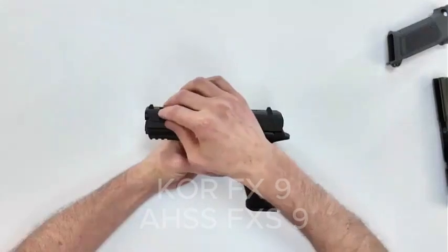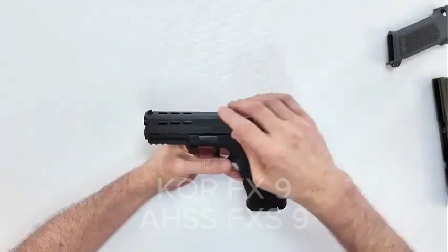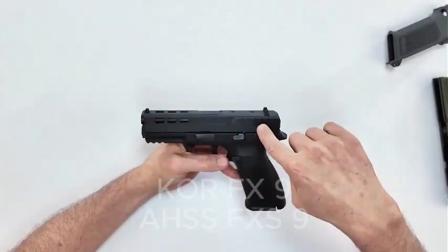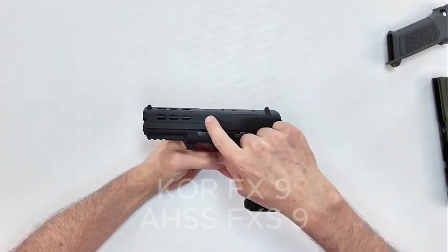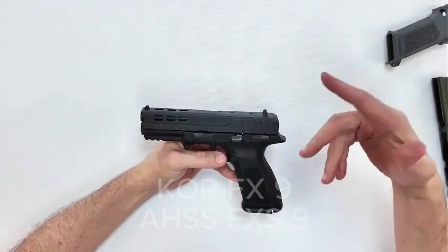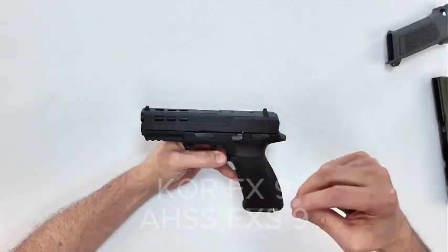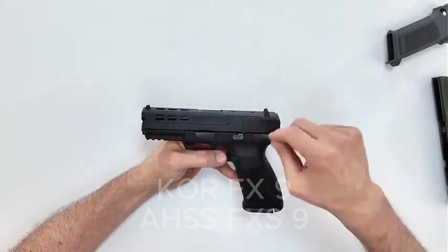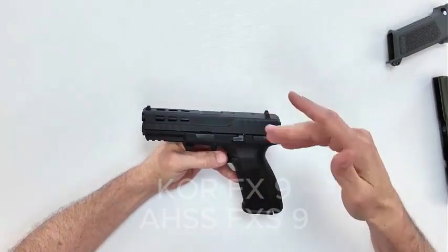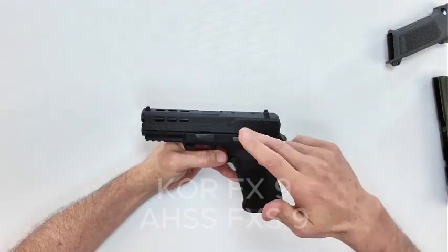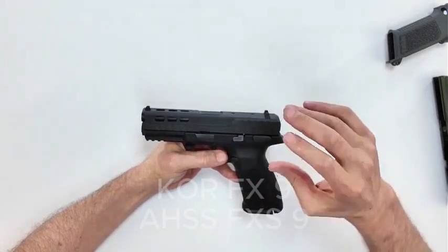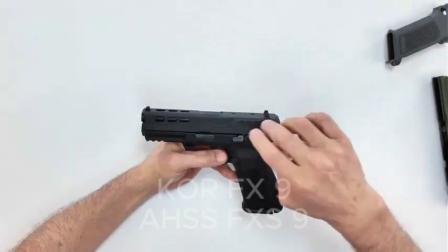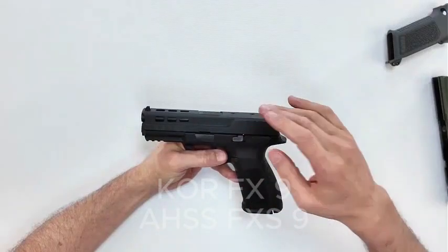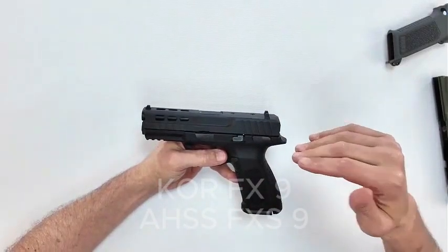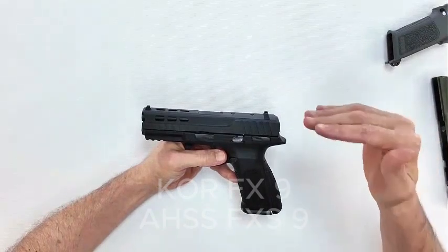After machining the material from the 10mm rod, when machining the barrel and mechanism, heat is generated on the surface. Because of this heat, a difference occurs between the core hardness and the surface hardness of the material. In order to equalize this difference, that is, to match the core hardness with the surface hardness, we subject the barrel and mechanism to a special process. That is, we subject them to heat treatment.